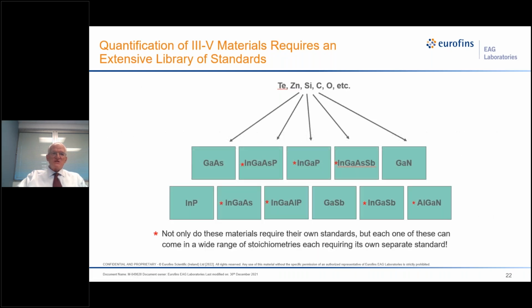But it gets really sticky with III-Vs. Again, why is it so complicated? If you have dopants here, tellurium, zinc, silicon, carbon, an impurity of oxygen, you want to analyze all of these in III-V structures. Well, it's not just gallium arsenide or indium phosphide or gallium nitride. You have all of these mixed stoichiometries. So you need standards for all of these, and to make matters worse, the starred matrices can come in a myriad of different stoichiometries. So you really have to have a standard for everything.